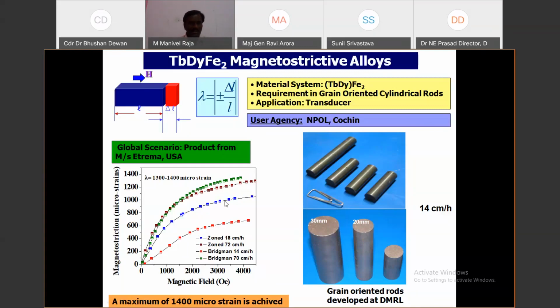And this is the typical characterization curve of the material. Magnetostriction is measured as a function of magnetic field. You can see that a maximum strain of 1400 has been obtained in DMRL alloys.